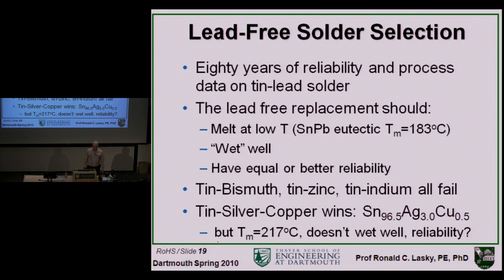So lead-free solder selection. Well, about 80 years of reliability and process data exists for leaded solder. So as soon as the electronics industry started being created, say in maybe even the teens and 20s, early radios and whatever, it was pretty much tin lead solder that people used. They used usually a eutectic tin lead solder because it melts at the lowest point. And so when people came to the point of wanting to get a lead-free replacement, everybody hoped we could get one that would melt at about the same temperature as tin lead eutectic solder, which was 183 degrees C. Wet well, what that means is when you get it near copper, it flows onto the copper and forms the intermetallic very well, and have equal or better reliability in reliability tests to make sure the solder joints would be robust. So this surprises a lot of people.